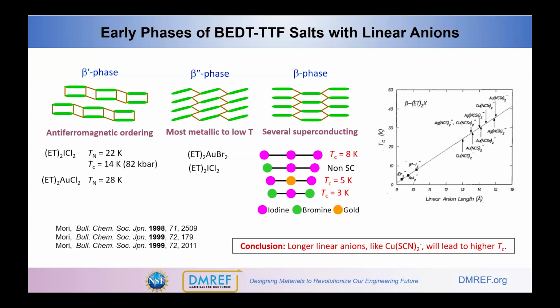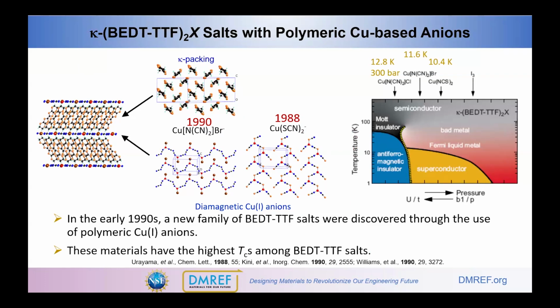And so a lot of other linear type anions were proposed, like copper thiocyanate, and you can read the list here. And so people set about to try to make superconductors with these longer linear anions. But what happens when you do that is that instead of getting the beta phase, you get a different packing motif, which is the kappa type salts. And in 1988, superconductivity was discovered in the copper thiocyanate derivative of ET at a little bit over 10 Kelvin. In 1990, copper dicyanamide bromide and chloride salts were discovered to have superconducting transition temperatures in that range, slightly higher.